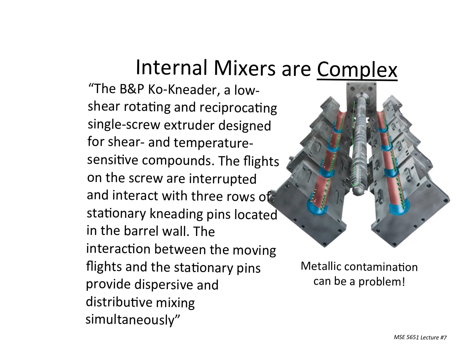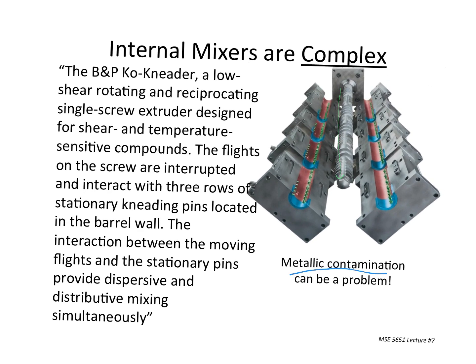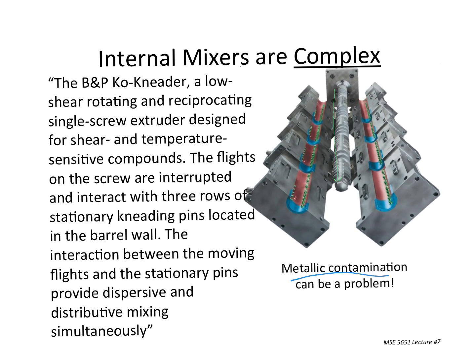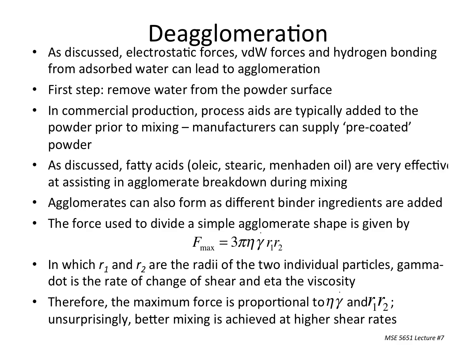lots of shear. If we try to do this with alumina, alumina will wear the hell out of something that's made out of metal. You might make this out of ceramic instead, which has been done. Hideously expensive when you do it, but it is a possibility because of what you're dealing with. You can't use steel and alumina. Pretty soon there won't be any steel left. The alumina will still be there, but the steel will be gone because it abrades the steel very quickly. But you know, this gives you an idea of what it is we're talking about. These are not trivial things to make.